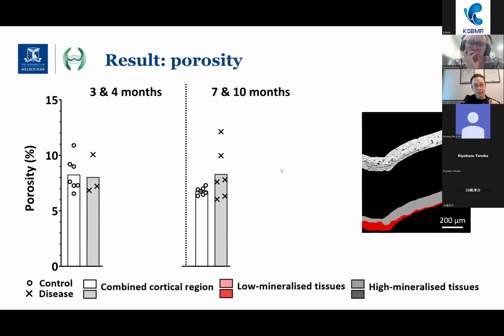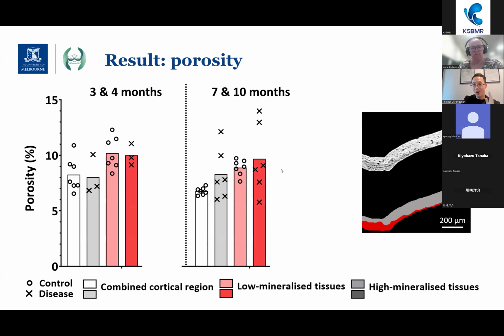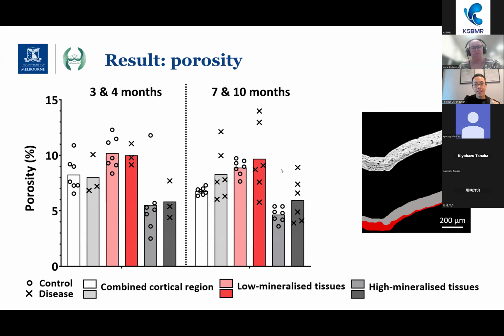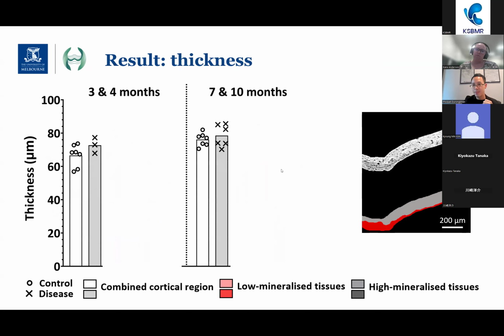Then if we can separate them in terms of porosity, you see that when I look at them combined, as we would see in micro CT, the combined cortical region, the porosity looks similar in the younger cohorts. That difference starts to come in the older cohorts on the right. However, if we split them into low mineral, you can see that in the low mineral tissue there is actually a jump in porosity in the older cohorts compared to the younger ones. And likewise, the higher mineralized region tends to be more dense and thus is reflected in this area with lower porosity.